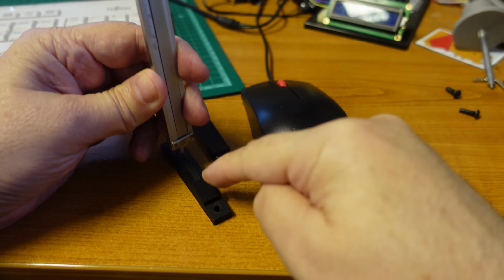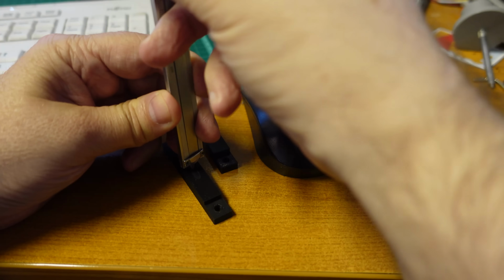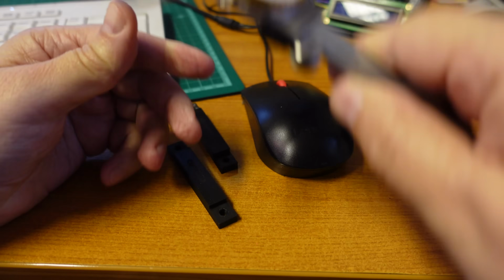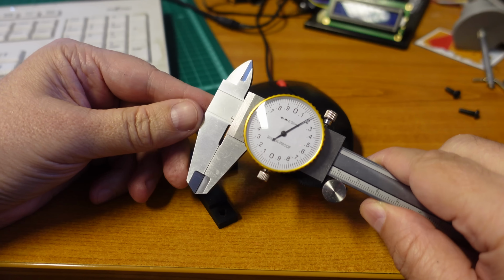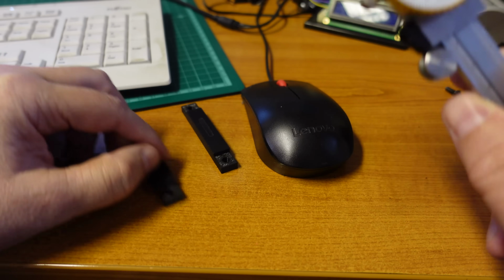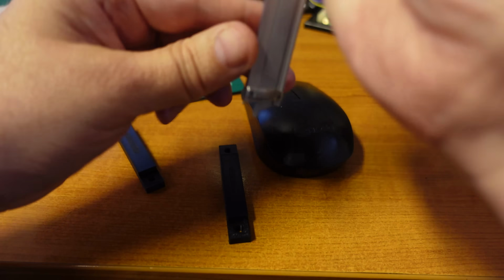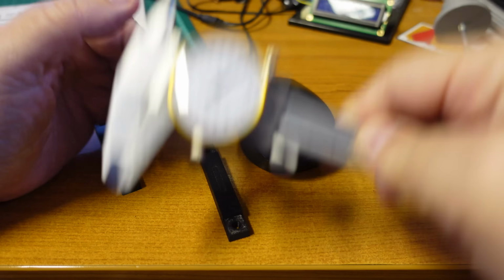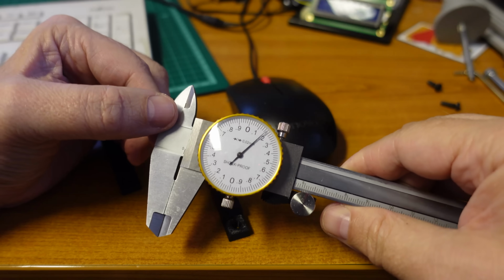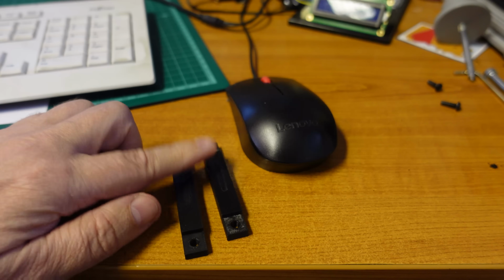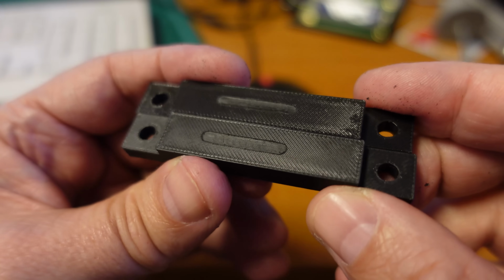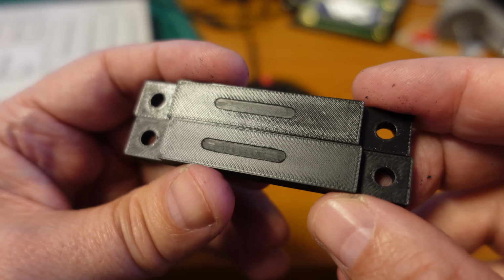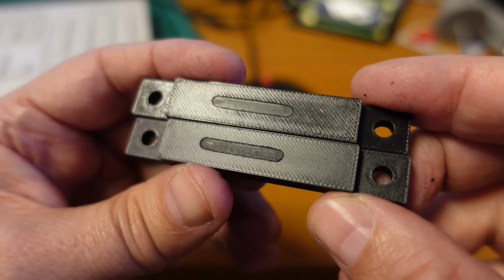It's time to measure the depth of the groove. This is PLA. 0.18 millimeters. And now PETG. Similar, 0.18 millimeters, and these are very good values actually. For average PETG, this depth would be approximately 0.5 millimeters.